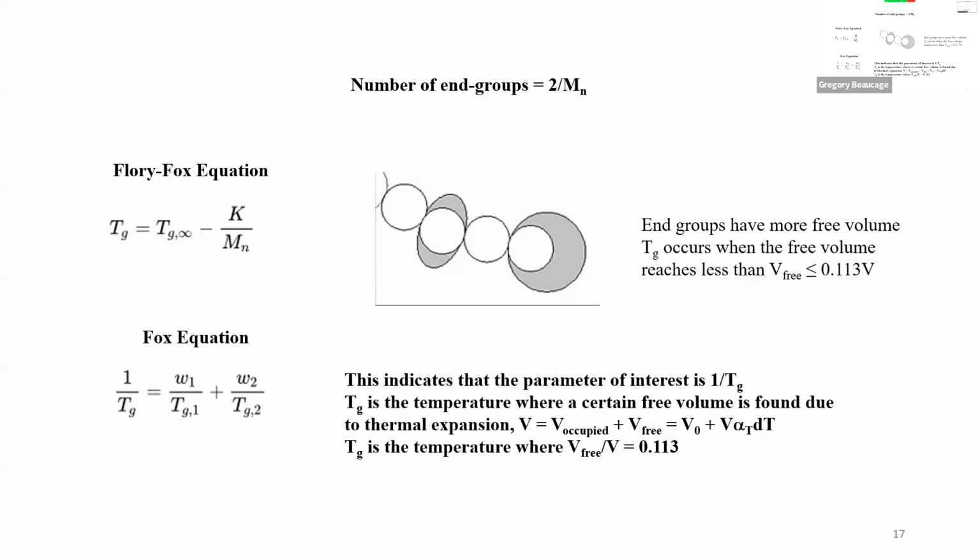So you can't measure it. You don't have a normal lab machine to measure the glass transition of polyethylene. It's semi-crystalline, and low density has maybe 40% crystallinity, and high density has maybe 80% crystallinity. This jug is high density, so it's a semi-crystalline material. That's why it's flexible. If it was a solid crystal, it would be like a rock. It's flexible because it's got amorphous zones in it. And the Tg is so low that it's just a liquid with crystalline bricks in it, right?